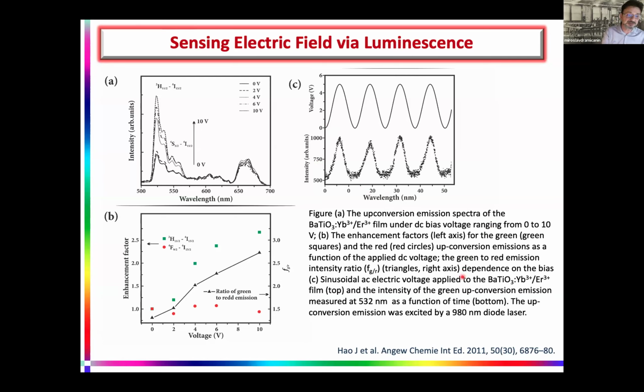And why this was so important for us is that the ratio of the green emissions here is actually one of the most famous tools to measure temperature. Trivalent erbium is the most well-known luminescence Boltzmann thermometer. And since luminescence is cross-sensitive to both temperature and electric field, this type of probe is actually very good, because one can use the ratio of the two green emissions to correct the ratio of green to red emission, which serves as a measure of the electric field applied to ferroelectrics.